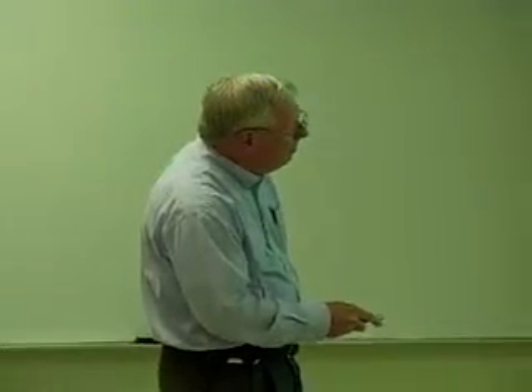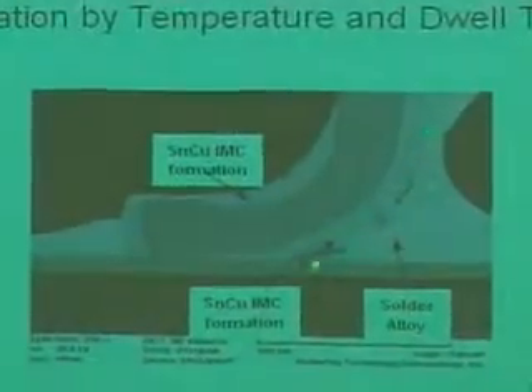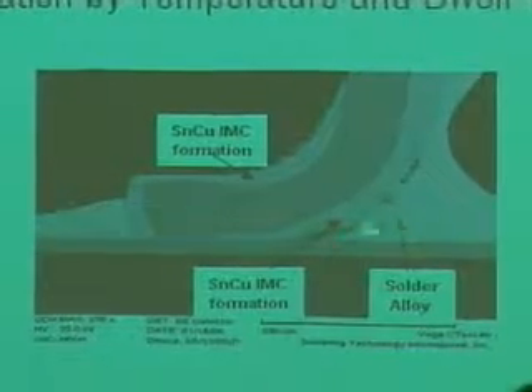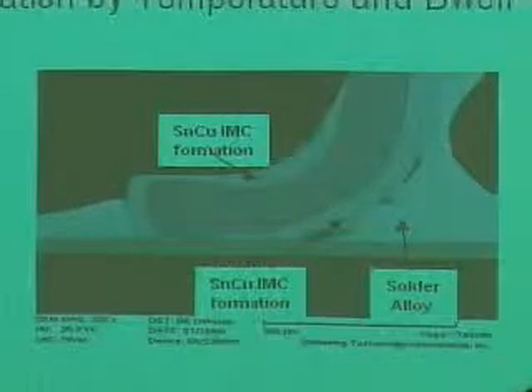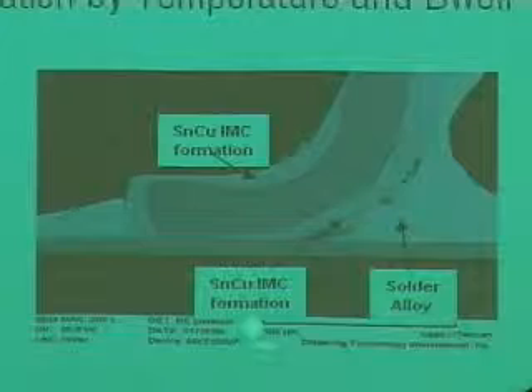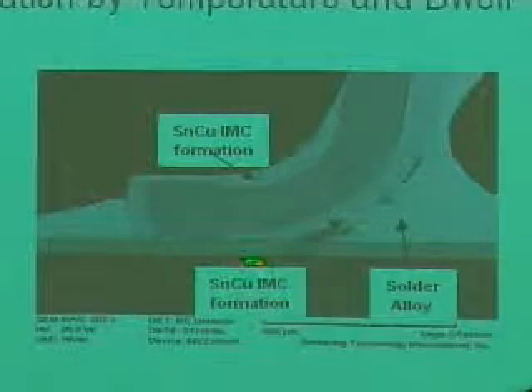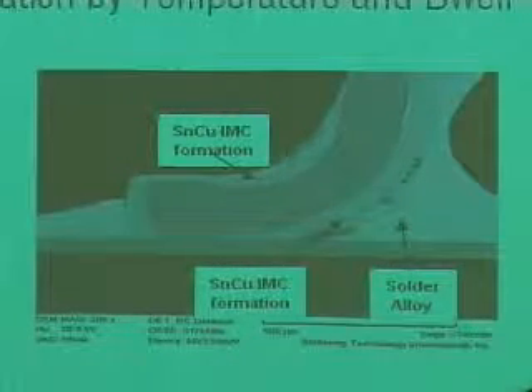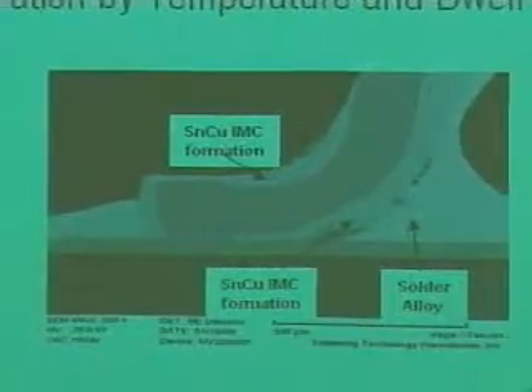Here's an example, the cross-section, where you can see here are the intermetallics. This is actually the lead itself on an integrated circuit. And the lead is bent, so it's a little thinner there. This is intermetallic formation, tin copper intermetallic formation along here. You can see there's a boundary, and you can see there's some voiding that has occurred there. And these intermetallics and the voids will weaken that solder joint. That's what we're concerned about.